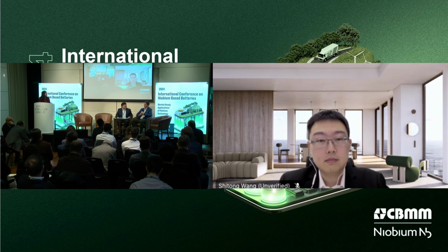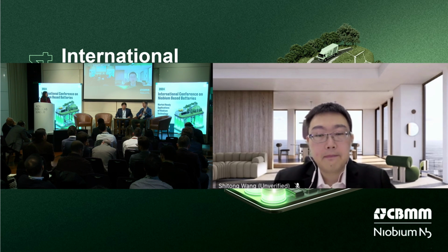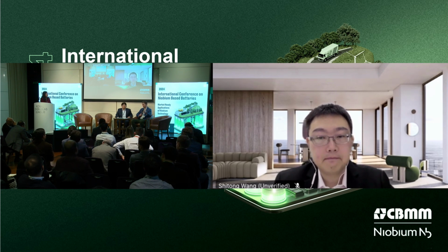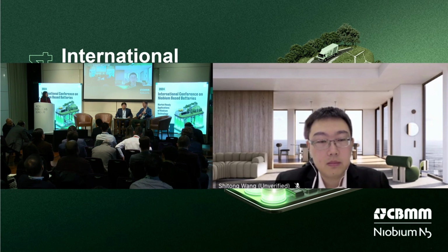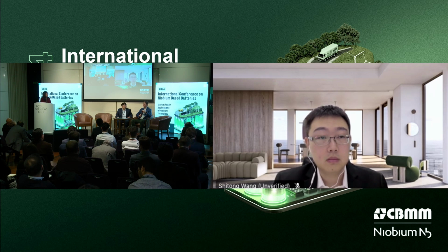Yeah, so we measured them up to 20C, which is kind of the convention now. This is a brand new material, literally never been reported as a battery. When you're working in that space, we're not doing cell optimization. These are half-cell coin cells because it's the first cells ever made. In my experience, going beyond 20C, you start to run into things that have nothing to do with the active material.